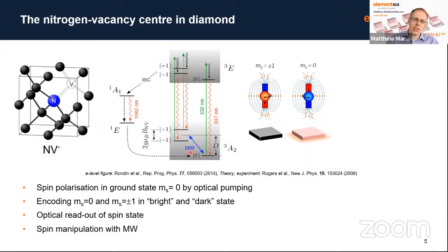And then this transition here is a microwave transition, so you can flip that spin state simply by application of microwaves. The readout process uses the same kind of mechanism: you get more light from this state than you do from going around this other route, and therefore you can read out the spin state simply by measuring whether it's a dark state or a bright state, allowing you to read out which spin state you're in.